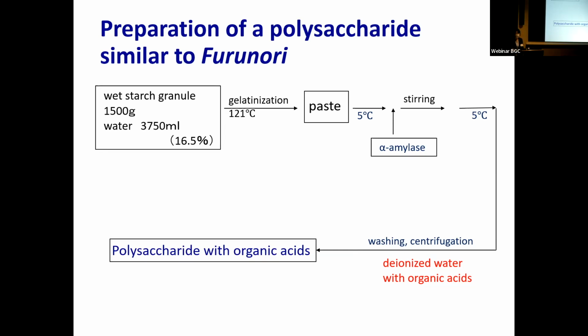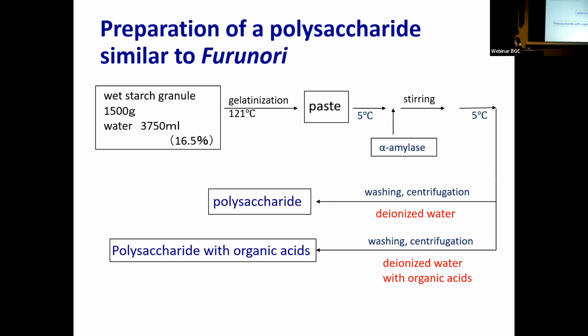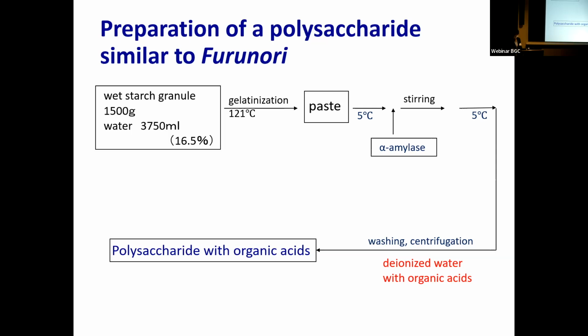Based on this deduction, we aimed to prepare artificial furunori, a polysaccharide similar to furunori. We did so by initially storing it at a low temperature, about 5 degrees centigrade, to form retrograded paste, and subsequently mixing in alpha amylase. The last stage involved washing the paste to remove intermediates with water containing organic acids. The resulting material showed very similar characteristics to furunori, which supported our assumption. We were able to acquire a polysaccharide similar to furunori within just a few weeks, thus drastically shortening the traditional